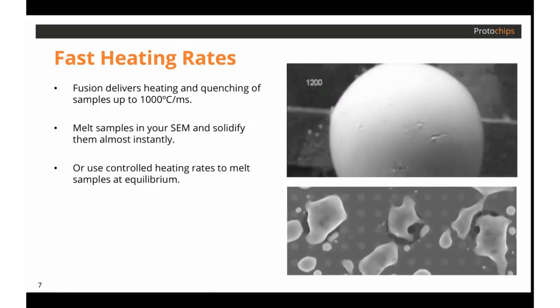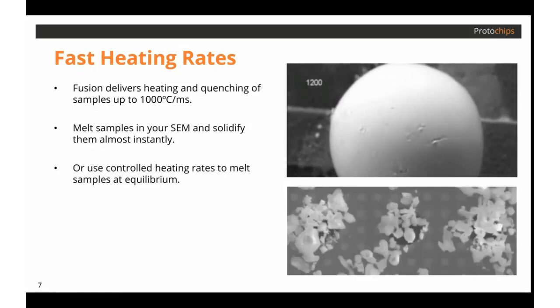So here you can see the temperature of a glass frit sample being increased just a few degrees Celsius per second until the glass begins melting at its liquidus temperature, which is about 650 degrees C. So obviously, thermal and heating studies are really important for in situ microscopy, but Fusion, as I mentioned earlier, can also be used for electrical studies.